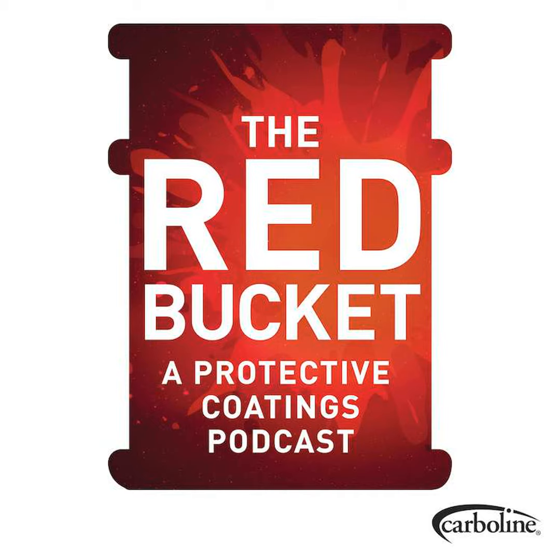And I think one of the things that it starts with is the inspection of concrete before you do anything. Let's talk a little bit about moisture in concrete and why moisture can be a problem. Well, especially if you have coatings that are very sensitive to moisture. Sure. Wrong coating system. Correct. And not all epoxies probably are the most tolerant, but you also have other things that you can do. And some of them, the simplest way I always tell somebody is do the plastic sheet method. You use a little visqueen 18 by 18 square, you put it at every 500 square feet, and it'll tell you. But that's moisture vapor and plastic sheet method and relative humidity probes typically are only very valuable when you get into an enclosed building where we have HVAC, heating, ventilation, and air conditioning that's going to be work because Mother Nature likes to hit an equilibrium. Yes. And so that's where we run into a problem. Now, when you get outside, when it can be diffused in all directions, that's where it gets much tougher.